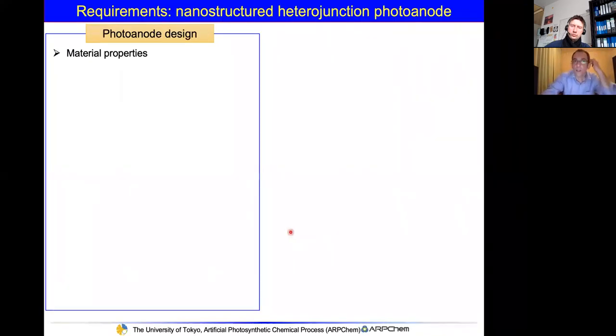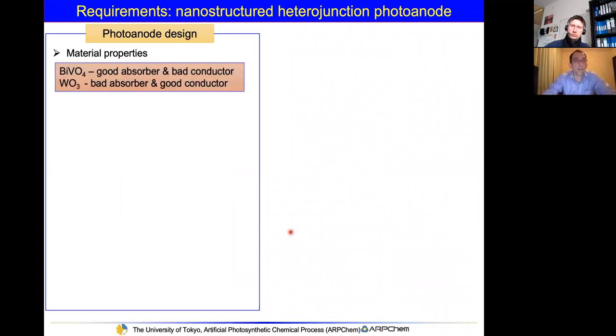In order to do that, I first considered the photoanode design, thinking deeply about the material properties. What do we know about bismuth vanadate? It's a very good absorber, however a bad conductor, which means the diffusion length of holes is very short. On the other hand, tungsten oxide is a bad absorber but a very good conductor. So if we combine these materials together, we can create an excellent photoanode material.